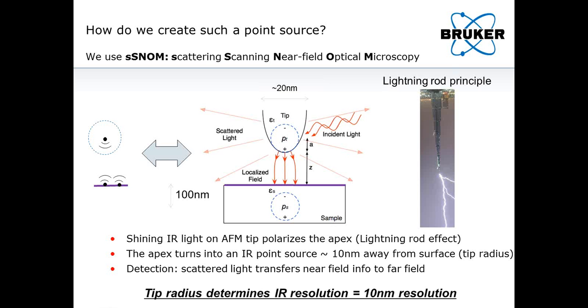The key takeaway here is that the tip radius is what determines our infrared resolution, not the wavelength of the incident light. The wavelength can be 10 microns, 2 microns, or 20 microns. As long as your tip is about 10 nanometers, you'll achieve 10 nanometer resolution because of the lightning rod principle and the evanescent waves you have access to.